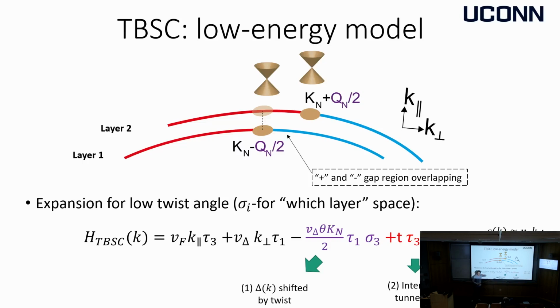So you have Dirac cones. Tau 3, tau 1 are particle-hole space. Tau 1 is the superconducting order parameter coupling particles and holes through the condensate. Then there is a term associated with the twist, which shifts the position of the zeros of the superconducting gap in opposite directions in 2 layers. And finally, there's an interlayer term, sigma stands for layer, interlayer tunneling of electrons and holes. So that's just a 4x4 matrix, which you can diagonalize, and I will walk you through what happens.